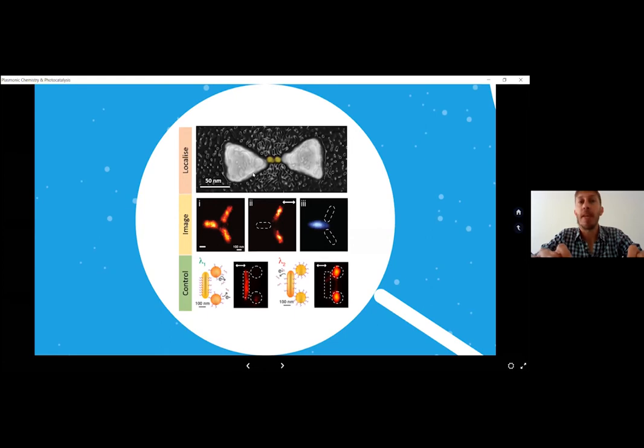After that, we moved into something a bit more elegant, and we tried to image the chemical reactions by using super resolution microscopy, so below the diffraction limit of light. Here, we have these trimer structures, so three rods. And when we illuminate with the polarization that matches one of the rods, we could displace the molecules on the surface, and we could replace that with another given molecule. Again, this image that we are seeing is below the diffraction limit. So we are looking inside the diffraction limited spot of the light, and we can release molecules within the spot by using the trick of exciting carriers in these plasmonic nanostructures. This could open a door to functionalize given surfaces selectively at the nanoscale with molecules.